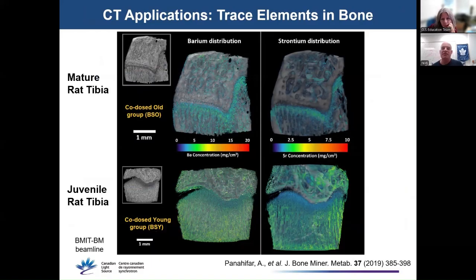Computed tomography is very important for studying bone and skeletal issues. This was a study looking at the incorporation of trace elements like barium and strontium in bone. Barium and strontium are similar to calcium, so they can substitute for calcium in bone. And this makes them very useful for tracking changes in bone. In this case, they were looking at barium and strontium incorporation in rat leg bones, including mature rats, which are finished growing, and juvenile rats, which are still reaching full size. So the rats were given extra barium and strontium in their diets.